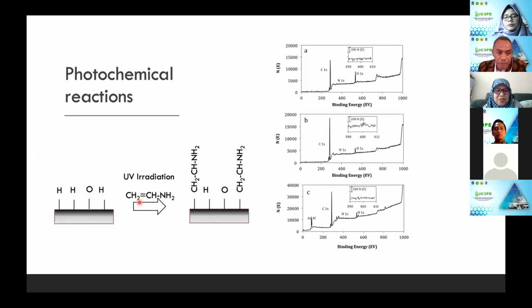Thank you. So we have a double bond here. By UV irradiation, these double bonds can be broken, and then one side here will be attached to diamond. Then we can get a nitrogen termination diamond. So how can we prove this reaction occurs? We can use XPS to see here before the photochemical reaction without nitrogen. Here we will have some nitrogen, and after gold modification we will have gold here.